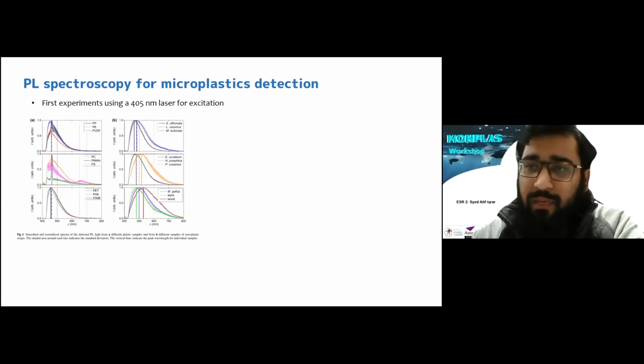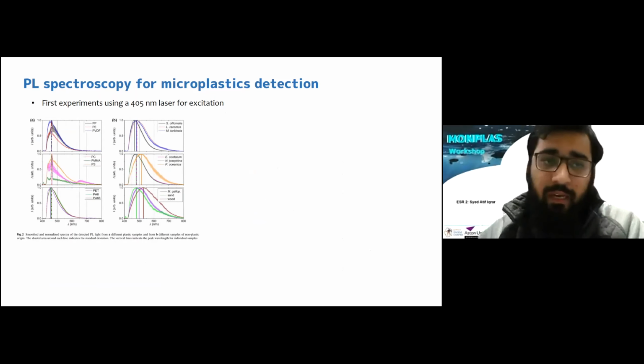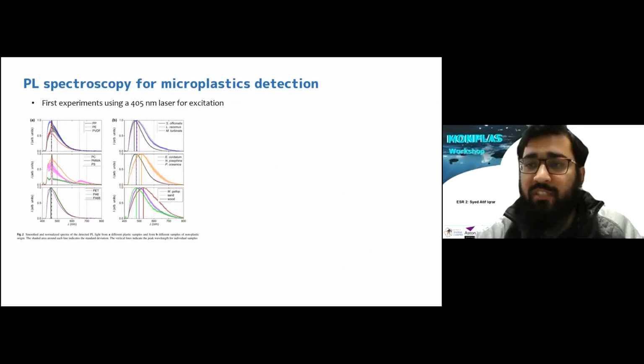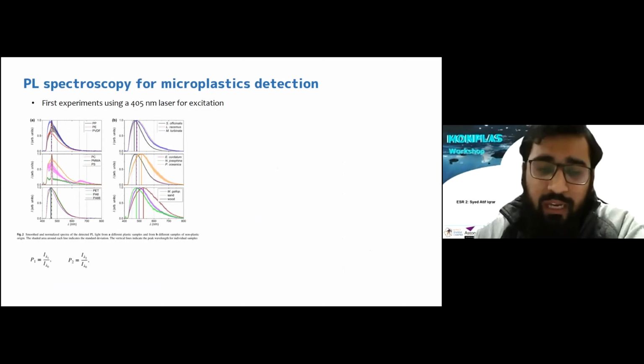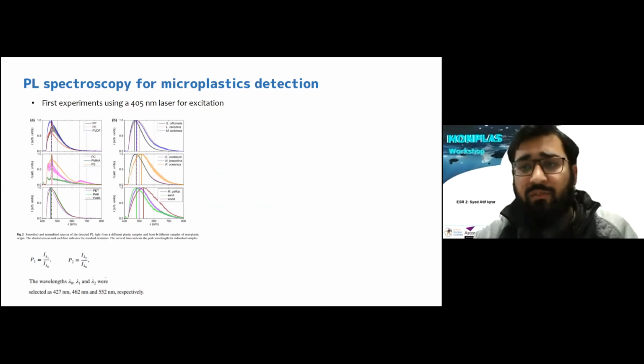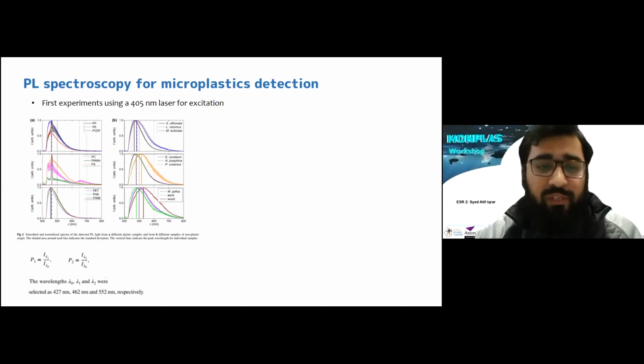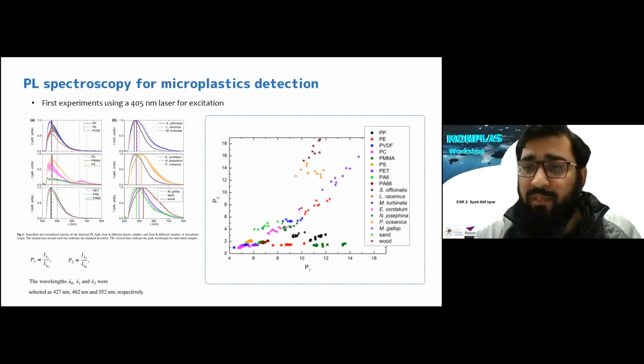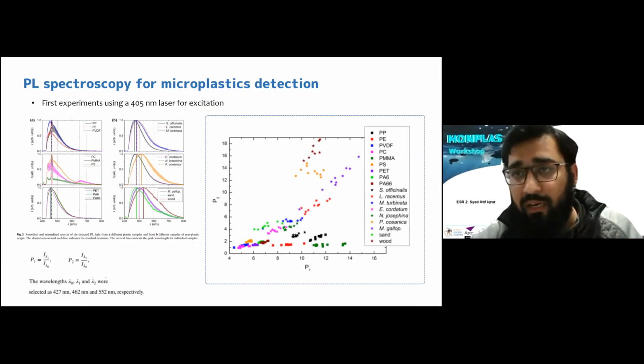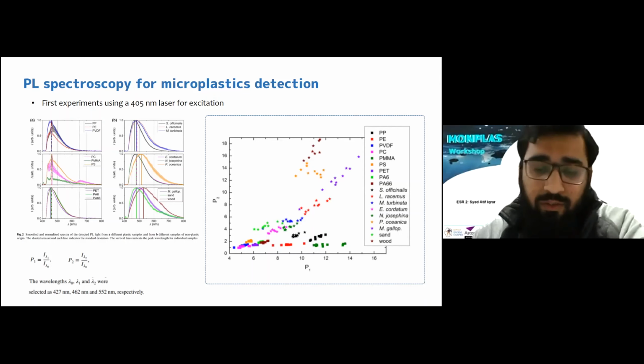Furthermore, they plotted the spectra, but the problem they faced is that it's really difficult to differentiate between different spectra. So for that purpose, they introduced 2 parameters that are basically intensity ratios, and they have taken the intensities at 3 wavelengths. The first one starting from 427, this is the minimum wavelength, and the maximum is 552, and they have taken one in between them. They plotted another graph based on these 2 parameters to differentiate between plastic and non-plastic materials, and they were quite successful in differentiating plastic from non-plastic using this PL spectroscopy.